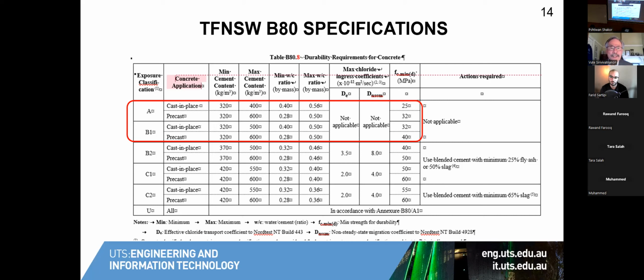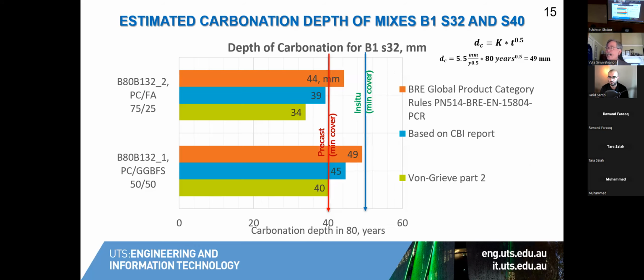So I will just quickly show this. This type of exposure usually refers to concrete that may be subjected to carbonation-induced corrosion only, okay, not a marine environment situation. So in this case, although there is no requirement on the performance-based type of specification, we are doing some work to see that, okay, if we produce concrete which doesn't meet the prescriptive requirement, can we also meet the durability requirement? And in this case it is carbonation-induced corrosion.